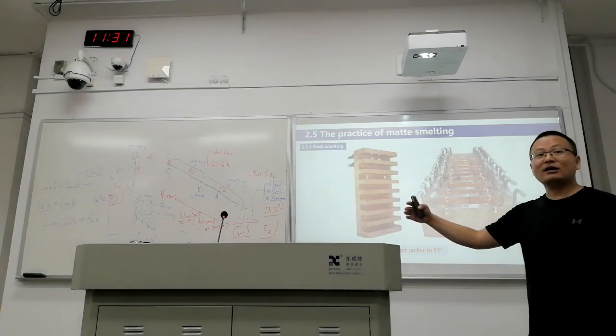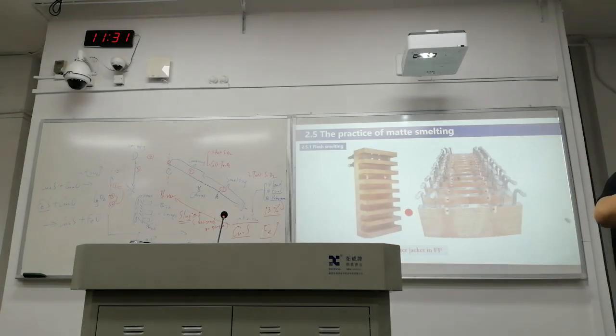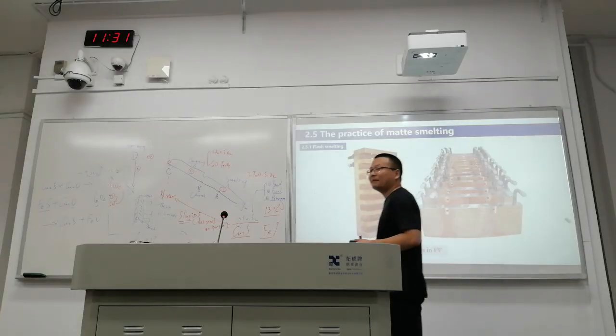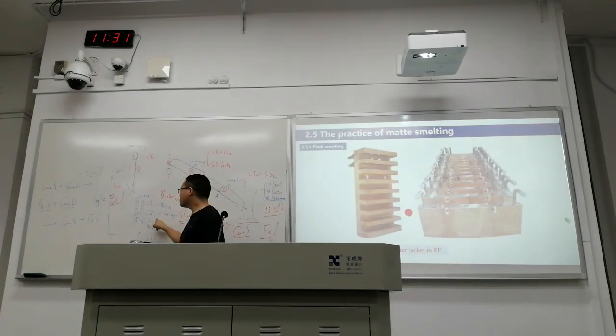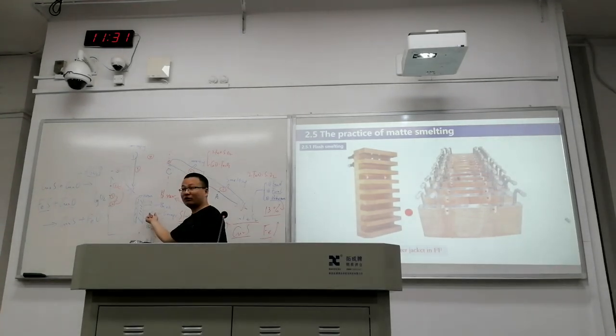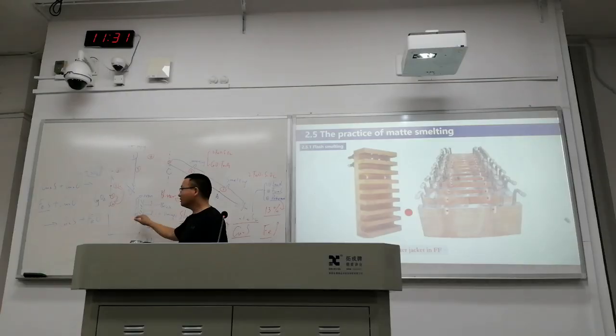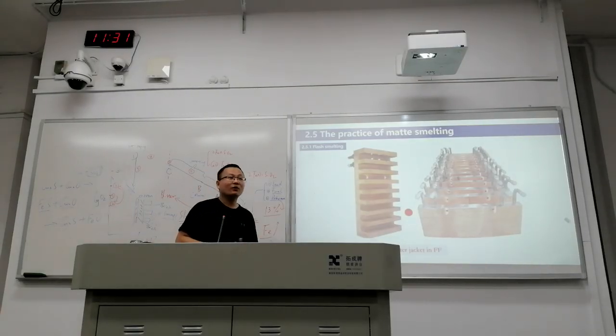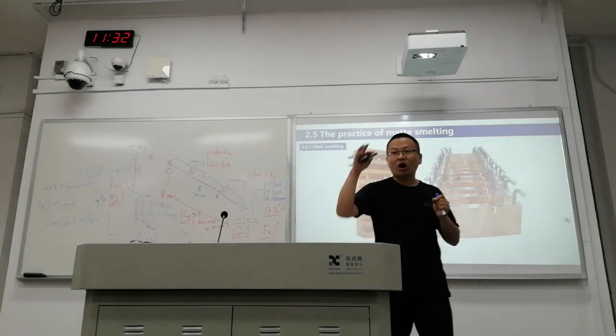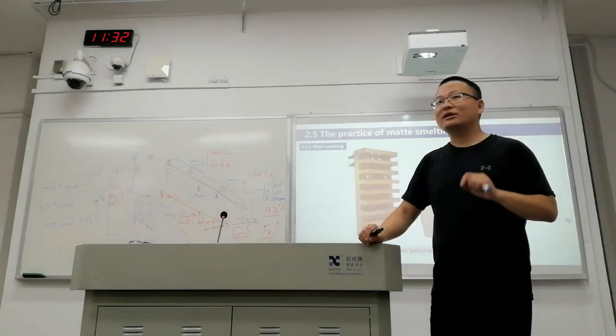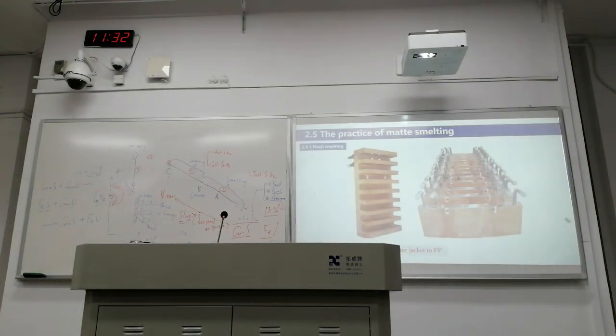So if there is a big furnace, you cannot measure the temperature from the slag, from the matte. You are not measuring that because you have several layers. It's not possible to measure it. So what should we do? We should always follow the temperature profile of the furnace. What should we do? We measure the water. If some pipes' temperature keeps increasing, what does it mean? It means there are corrosions or they are destroying this lining and the bricks. The distance is smaller. We are getting more energy or thermal from the furnace. So the water in this cooling element will increase dramatically. So this is a very, very top-level risk of accident. So this is something we should pay attention to. So, water cooling jacket.